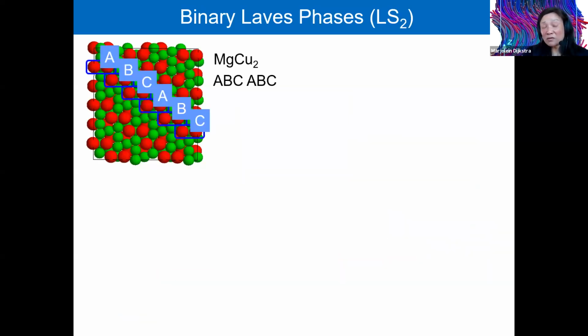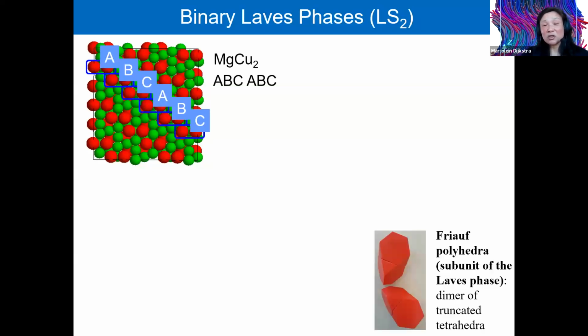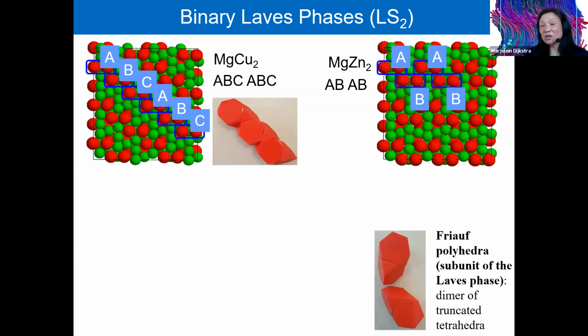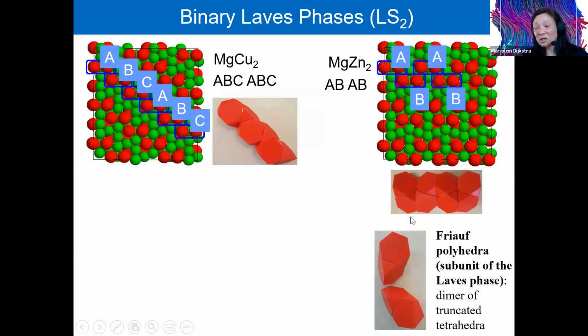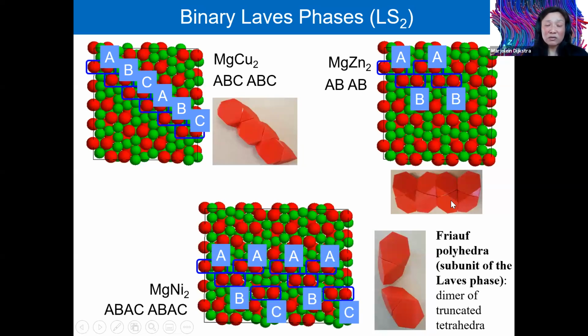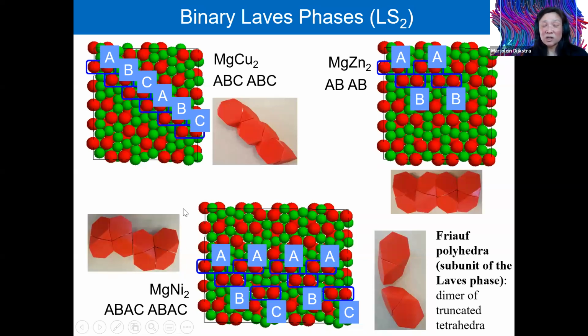In the case of these Laves phases, these Friauf-Laves polyhedra are stacked in an ABC fashion in the case of the magnesium copper phase, as shown here. In the magnesium zinc phase, they are stacked in the AB fashion. So here we've 3D printed many of these truncated tetrahedra just to understand these crystal structures. In the magnesium zinc phase, it's an AB stacking, so it's a sort of zigzag stacking. In the case of the magnesium nickel phase, it is an even weirder zigzag stacking